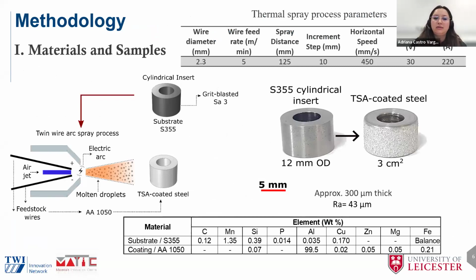So here we can condense basically the procedure. We machine cylindrical inserts from an S355 rod, and we obtain the coating using the parameters that you can see on the top in this table. It's a cylindrical insert with 12 millimeters of outer diameter. So in that sense, the surface under study will be 3 centimeters squared. And actually, you can see the coating here.